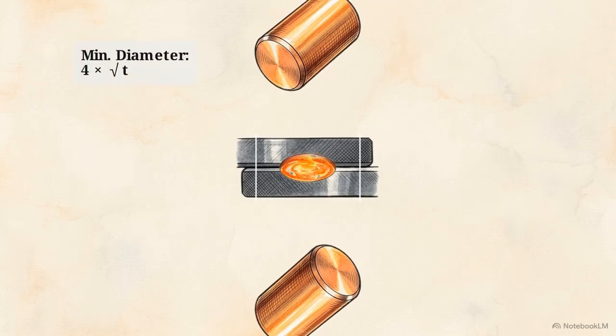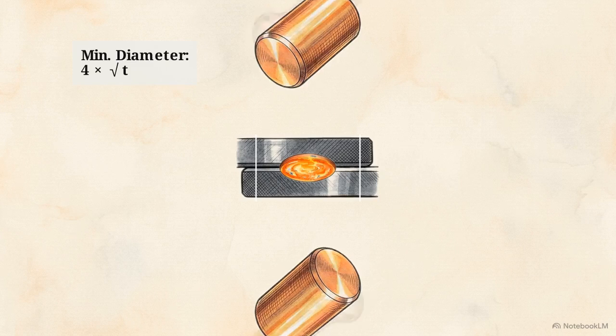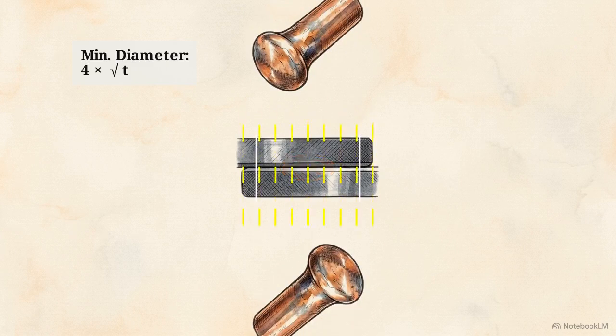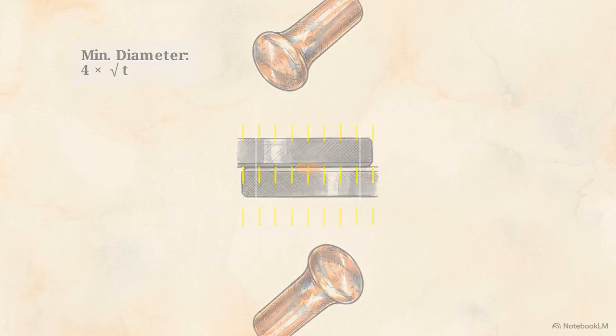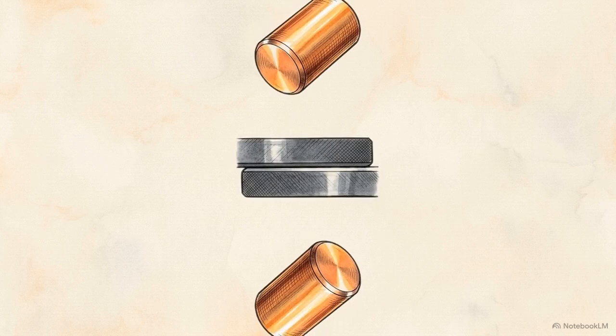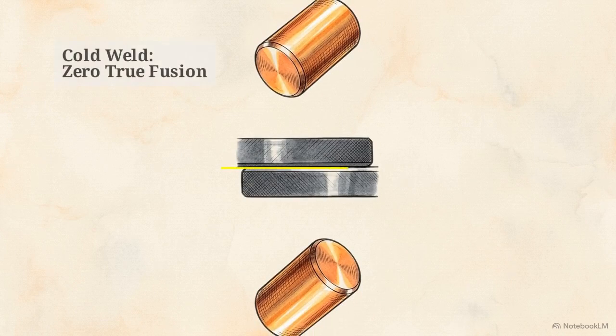In a different scenario, an undersized nugget occurs entirely internally. The melt pool forms but stops expanding. It fails to reach the required minimum diameter, which is generally calculated as 4 times the square root of the sheet thickness. This is the direct result of those worn, mushroomed electrodes bleeding off the current density. The most deceptive defect is the stick weld, or cold weld. The heavy mechanical force compresses the sheets tightly, but the faying surface never reaches a molten state. The metals touch, but there is zero true fusion.